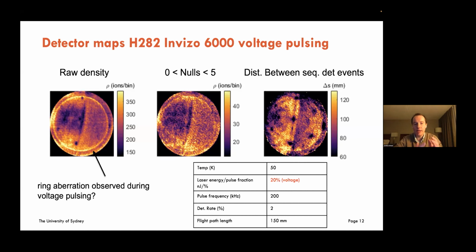So this was actually an experiment run in voltage pulsing mode. The vast majority of experiments will be doing laser pulsing, but we do have voltage pulsing capability. I was observing a strange aberration, and we're still a bit unsure as to why that might be happening, whether that was a problem with the electrode, but others were observing that too. At least for the voltage pulsing, we're getting comparable crystallographic information to what we were observing in the LEAPs. This was running at a little bit of a higher temperature as well, compared to the one that I showed before.